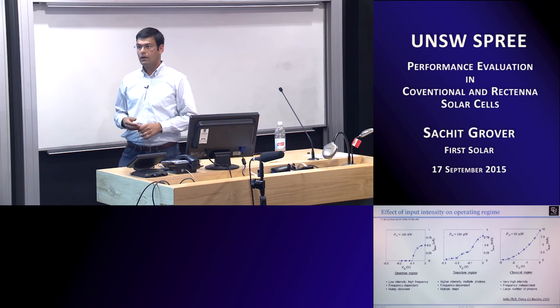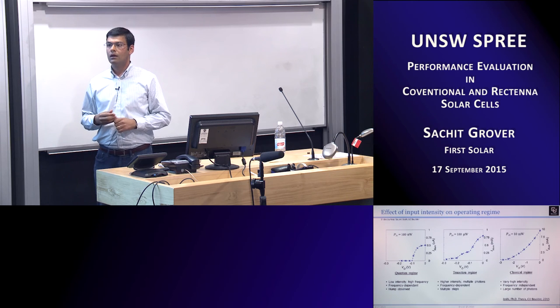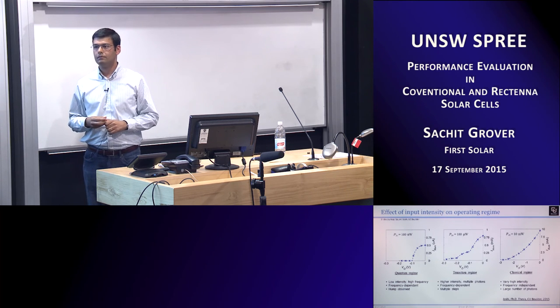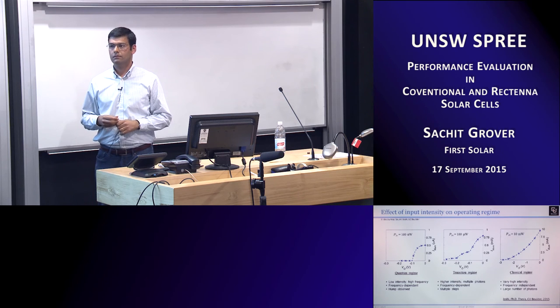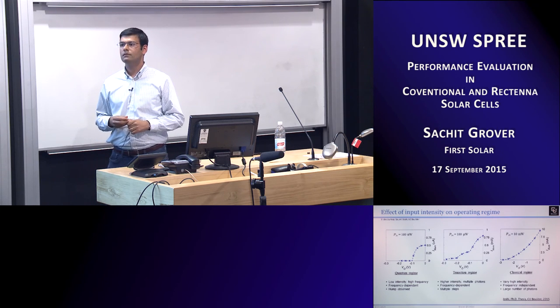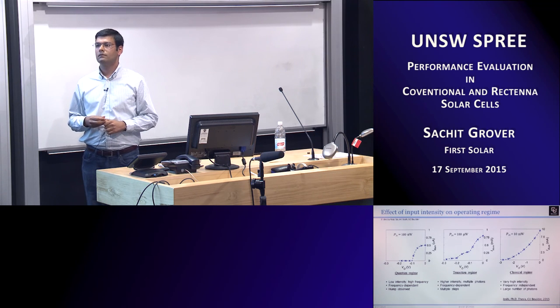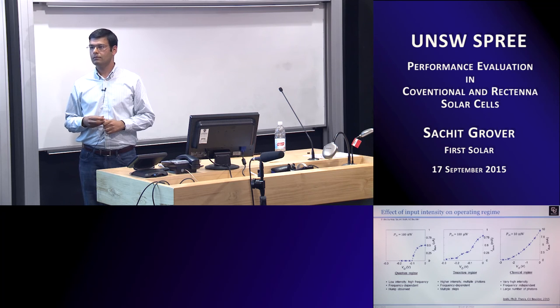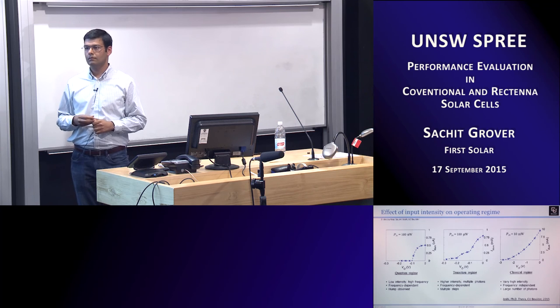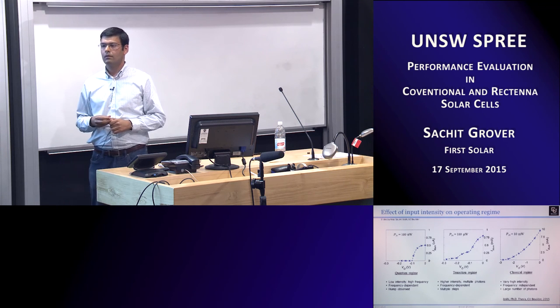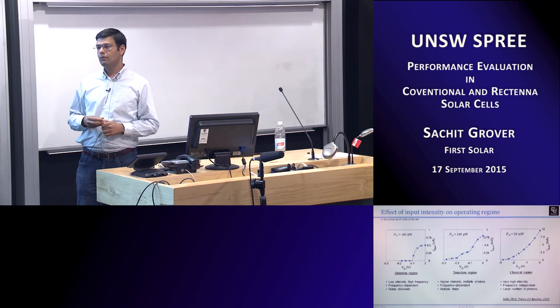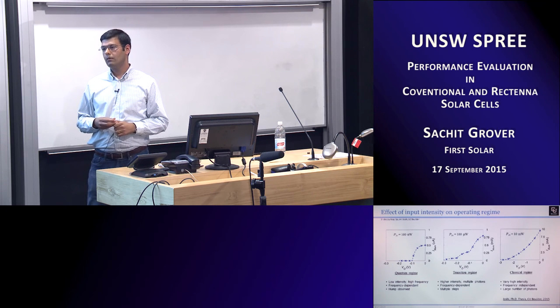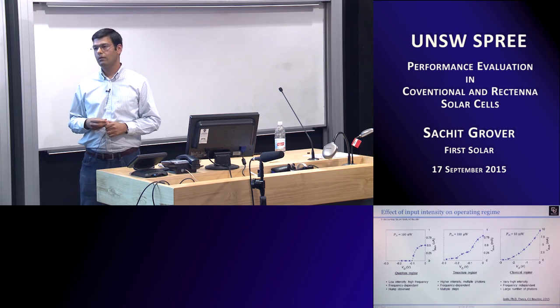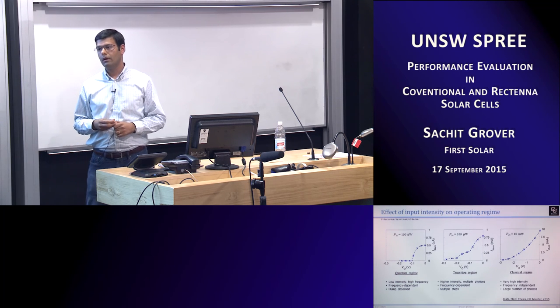I think there's a very similar approach that could be used. The same thing is also done with inorganic heterojunctions sometimes, because they are often limited by the interfaces, where the band offsets are pinned. Essentially the same approach is often used, but it doesn't have to be. As you say, it depends on the activation energies for those different recombination mechanisms. So I think it could be used, and it would be very nice to try. There's a very big disconnect between the two approaches at the moment, so I think that would be very useful.